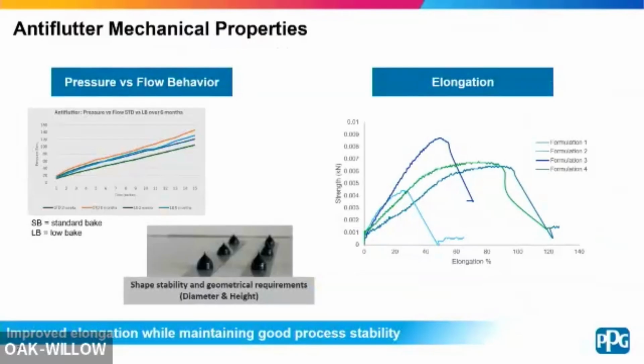So just to show a snapshot of some of the mechanical properties of these anti-flutter technologies. So this is a graph showing pressure versus flow for our standard bake formulations, as well as this expanded or low bake technology formulation space at both 2 weeks and 6 months. And you can see that the performance is very similar for pressure versus flow. And that's very important for anti-flutters, especially when you need to have very consistent and tunable shape stability. So you have a very specific diameter and height of your droplets that you might be wanting to apply, making sure that's very consistent over time. And so we're able to achieve that.